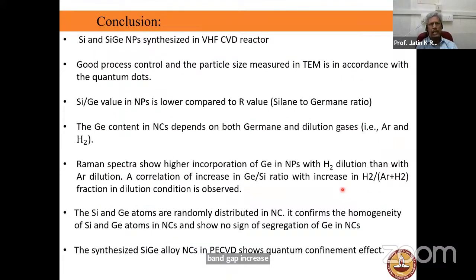So in conclusion, silicon and silicon germanium quantum dots have been synthesized in the very high frequency CVD reactor. There is good process control, and the particle size measured by TEM is in accordance with quantum dots. The silicon germanium values are lower compared to the ratio we put in, that is the silane to germane ratio. You don't get a similar ratio, but a slightly different ratio.